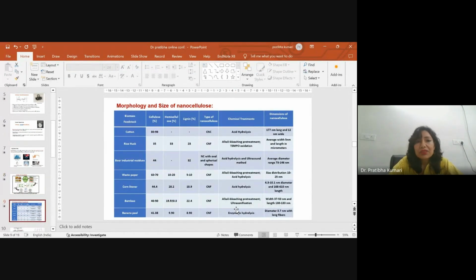Like in this table, we can see that if we change the method and the source, we can prepare different types of nanocellulose. If we take cotton as a source, in cotton there is 80 to 98% cellulose. If we apply the acid hydrolysis process to convert cellulose into nanocellulose, then we'll get CNC. CNC is cellulose nanocrystals. So we'll get the crystals of the cellulose.